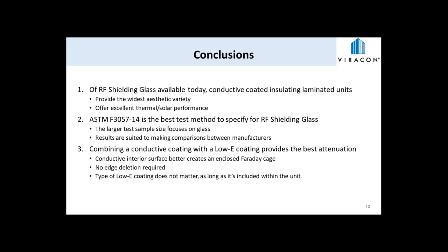The new ASTM test is the best test for RF shielding glass, as it focuses on the glass itself and allows for comparisons to be made between manufacturers. And utilizing an FTO conductive coating in combination with a Low-E coating provides the best attenuation, as the conductive interior surface better creates an enclosed Faraday cage due to no edge deletion requirements. And lastly, the type of Low-E coating does not make a difference as long as it's included within the unit, as this combination will result in the highest attenuation.